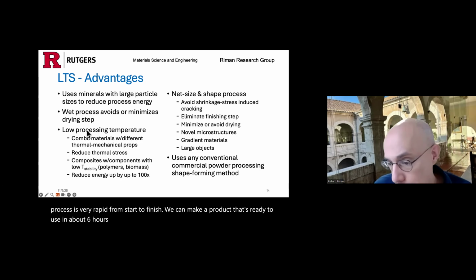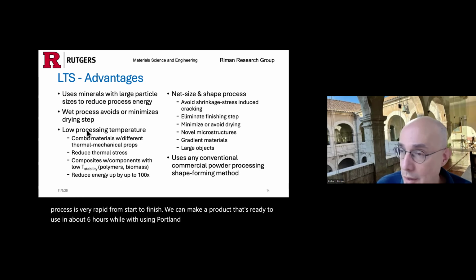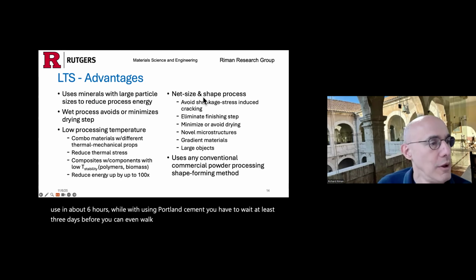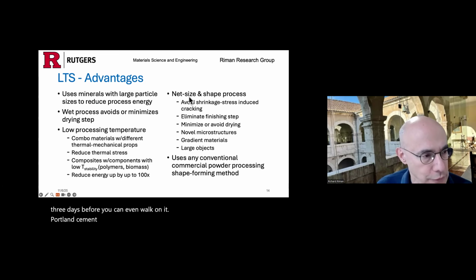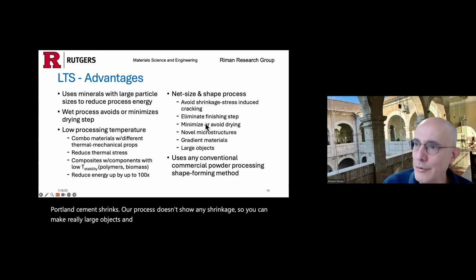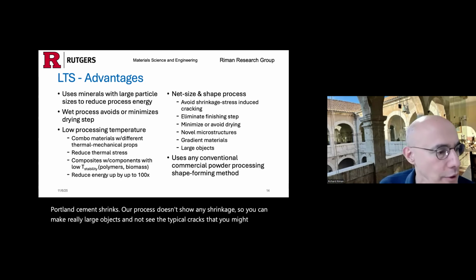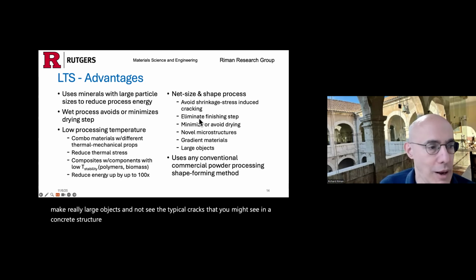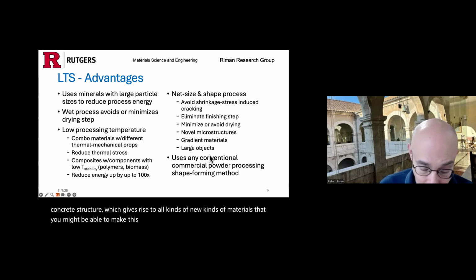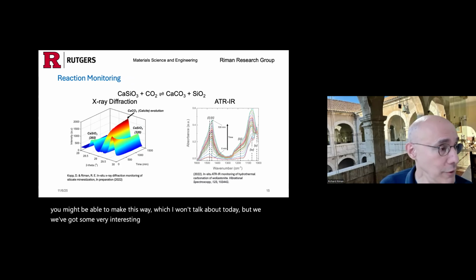While with using Portland cement, you have to wait at least 3 days before you can even walk on it. Portland cement shrinks. Our process doesn't show any shrinkage, so you can make really large objects and not see the typical cracks that you might see in a concrete structure, which gives rise to all kinds of new kinds of materials that you might be able to make this way, which I won't talk about today, but we've got some very interesting materials that have other uses.